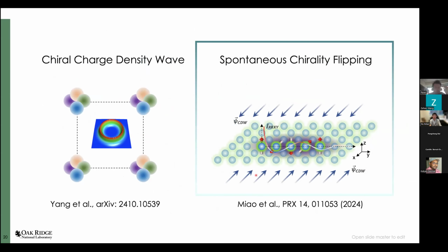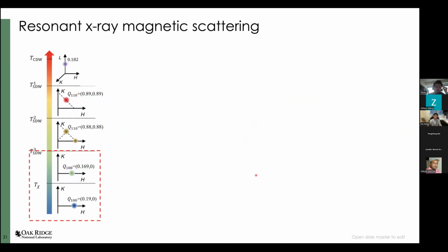All right. So now I'm going to focus on the spin density wave at low temperature. I just want to remind you of the zero field phase diagram. Indeed, around 15 or 16 Kelvin, the system forms a double Q spin density wave with a wave vector around the Q11 direction. And if you go through T2, then the spin slightly cants along the z-axis. So you're going to have a new superlattice peak along H or K, but it's still a double Q spin density wave.